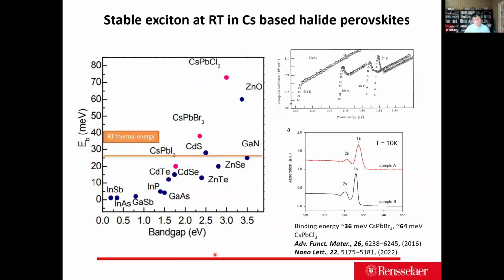So again, there's a stable exciton even at room temperature in the cesium-based halide perovskite material. For cesium lead bromide, the exciton binding energy is about 36 meV. For cesium lead chloride, the exciton binding energy is about 64 to 70 meV, depending on the measurement. Essentially, if you go down to low temperature, even with solution synthesis or CVD synthesis, you can already see the Rydberg exciton, essentially the higher principal quantum number exciton from n equal to 1, n equal to 2, and for some really great samples, you can even see something around n equal to 3. So you can start to see the Rydberg series. Compared with gallium arsenide at 21 Kelvin, the exciton peak is really pronounced.